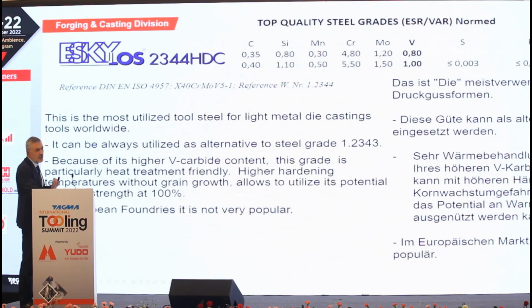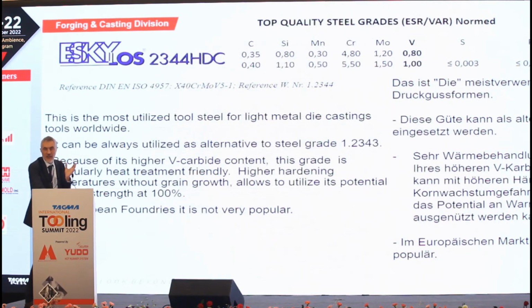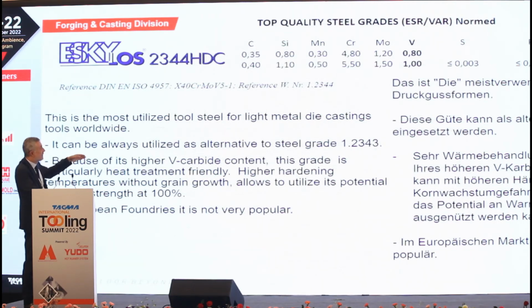2344, which is the most important here in India for your youth and for your culture. Okay. It can always be utilized as an alternative to 2343, which is more known in Europe, because of its higher vanadium carbide content, it is particularly heat treatment friendly. Higher hardening temperature without grain growth allows to utilize its potential in warm strength at 100%. In Europe it is not so popular.